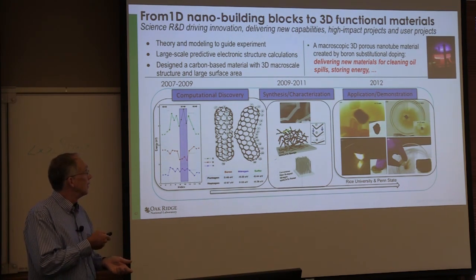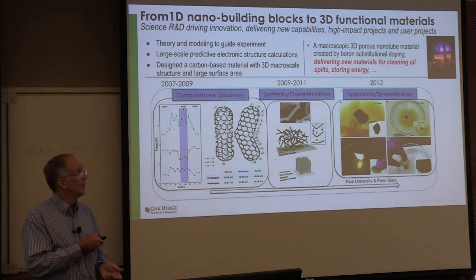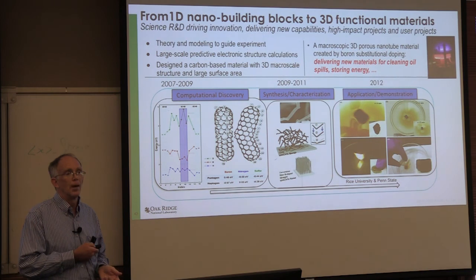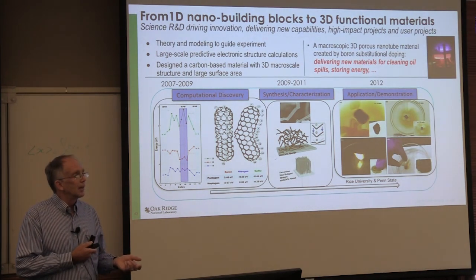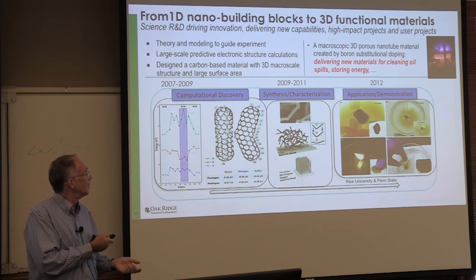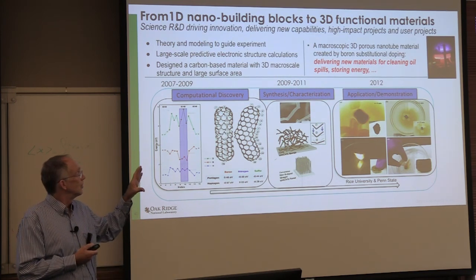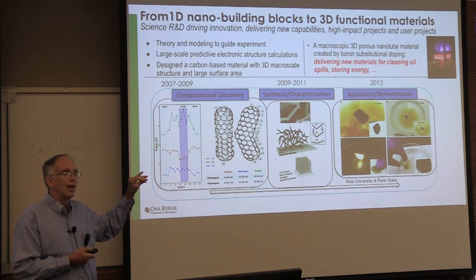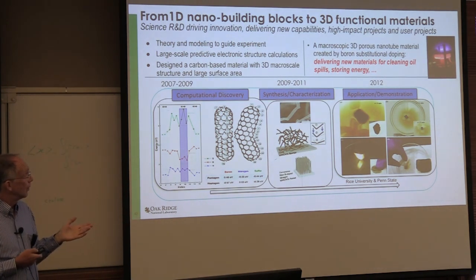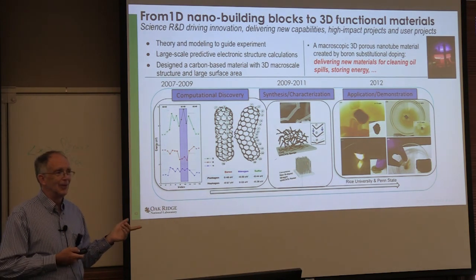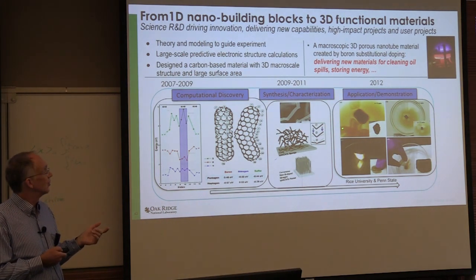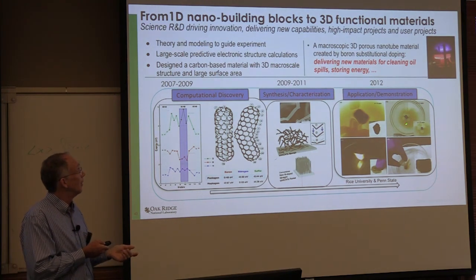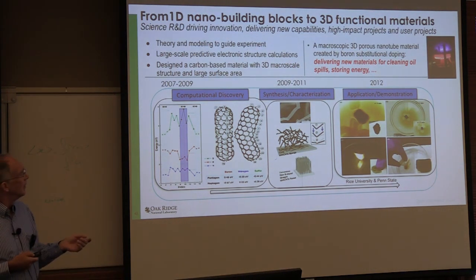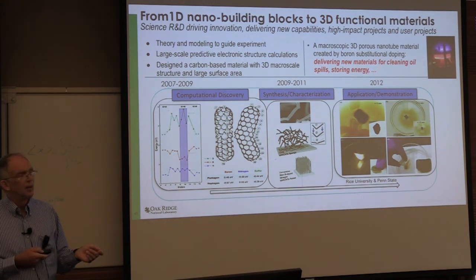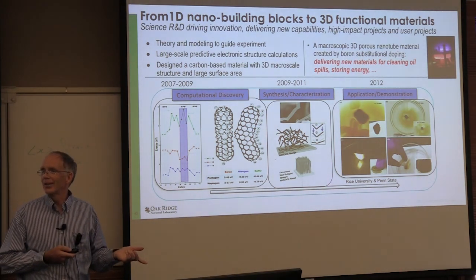So we dubbed that the great nanosponge because all the space is just like a sponge. It's a pore space. So it should act like a sponge, right? You should be able to put stuff in it and it should get absorbed in these pores. And you can squeeze it out because you can apply mechanical pressure. So one of the grad students working on this from Texas, believe it or not, went to the little gas station and got some oil, and then down to the Gulf of Mexico, got some seawater, and poured the oil in the seawater and said, look, that's carbon. Carbon doesn't really like water. It's kind of hydrophobic. But carbon likes oil because that's what oil is.